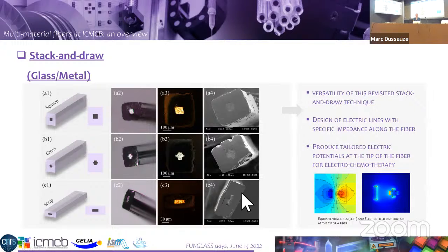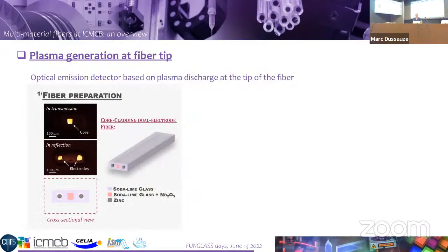So this is, I would say, a refinement of the method that can eventually be used if we want to not only have some electro-optic effect in the fibers, but on top of that, if we want to generate some specific tip effects at a really specific, localized point somewhere in the fiber. Here is an example of a brief simulation that was performed at the time. And now to give some examples of applications of this method.